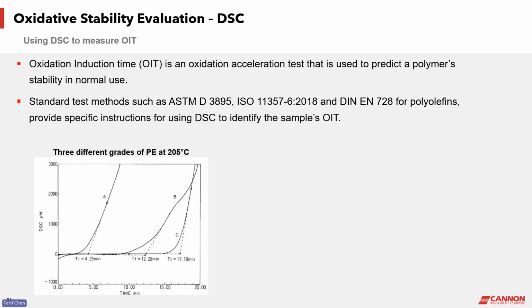After equilibrating at a temperature of 205 degrees C, we switched to an air purge, introducing oxygen into the DSC furnace. So the OIT time is defined as the onset point on the heat flow curve. From this comparison data, we can see that sample A has the shortest OIT, which means this sample has poor oxidation stability. This resin may need some additional antioxidant to enhance its stability. Sample C has the longest OIT, which means this resin is mostly stable against oxidation.